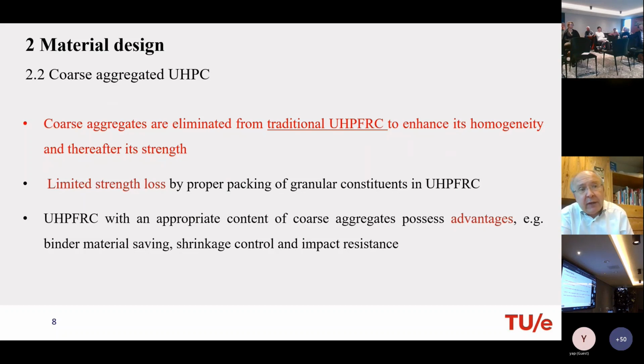Well, then we looked at the aggregates to introduce them in the mix, because that also helps in saving the fines in the mix. And normally coarse aggregates you will not find in UHPFRC. We saw it also in the previous presentations, which were mostly about paste, as we can call it, because there were no aggregates in it, or at most you can talk about mortar when 1 to 3 millimeter or 4 millimeter aggregates are included, but that's it. Well, we went higher, above this 2 or 4 millimeter, and we see that there's a limited strength loss. I will show you some details when we have proper packing of the granular constituents.